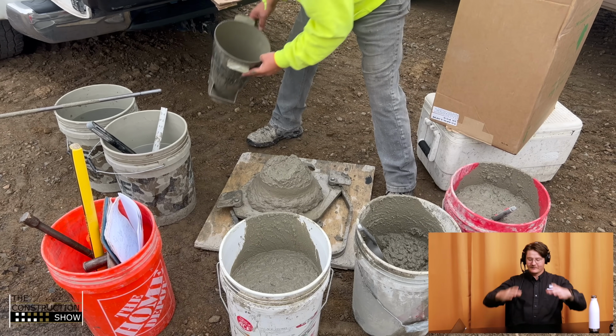In the lab, we can say we're looking for a water to cement or water to binder ratio of 0.3, 0.35 or something like that, to have that perfect workability and water ratio. They can't exactly do that at a ready mix plant. They need to add water to get it to the flow standard they need. When that concrete gets on site, an engineer will put it in what's called an Abrams cone, a stacked cone, and you pull it up and measure from the top of the cone how much the concrete has slumped, and that's your slump value.